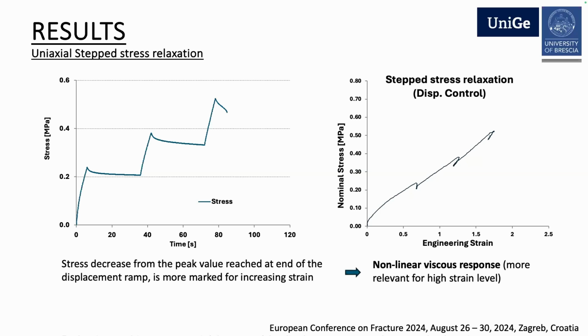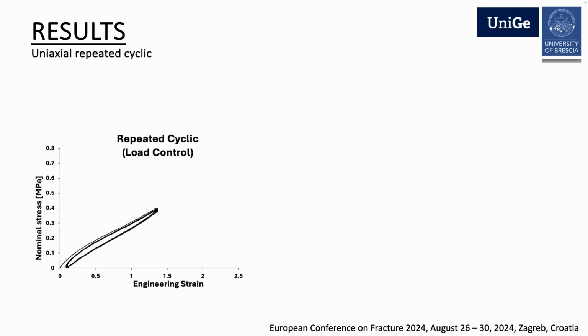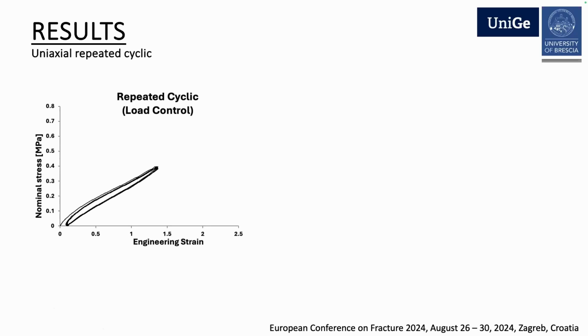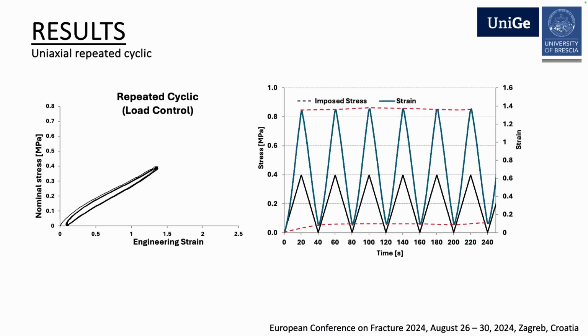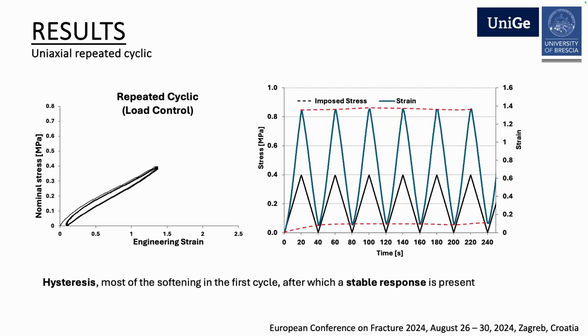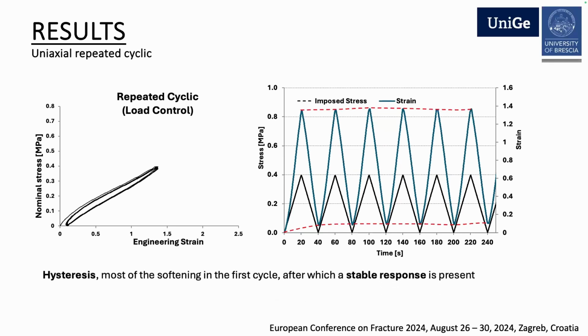We also observed a reduction of the strength, so the specimen failed prematurely with respect to what we were expecting. Now, considering cyclic loading, when the specimen is cycled over a fixed load level, there are some typical features like hysteresis and residual strain that we might expect for this type of material. And actually, the material exhibits some softening, not so marked, and apparently this is concentrated in the very first cycle, and then we get a stable response.